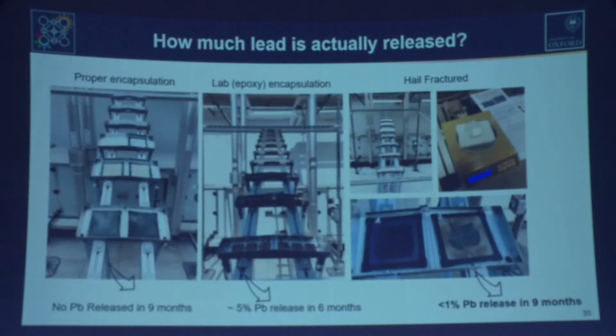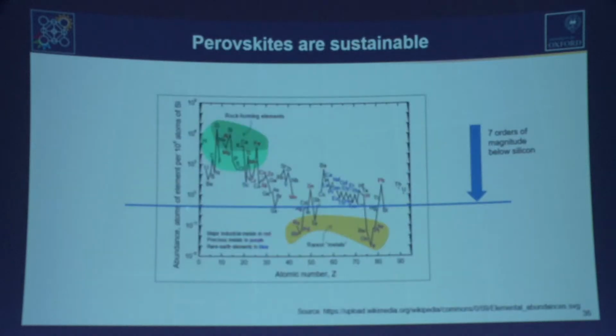Once more, modules that are put out into the field will be laminated and encapsulated. And we did some tests by cracking some mini modules with hail, simulating something that may happen in a big hailstorm, and left these cells outside. This was done in Switzerland, to be rained on for 9 months. And we found that only 1% of the lead in the module actually came out over a 9-month period. So basically, the normal lamination and encapsulation pretty much seals all the material in there. So we shouldn't be concerned about the use of lead in these modules.